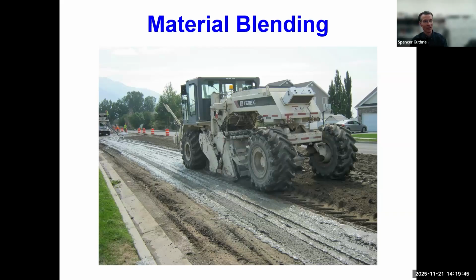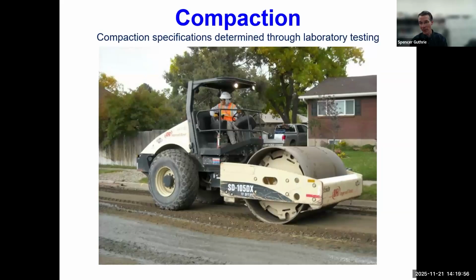So here's a picture. Again, no cement dust at all in a neighborhood, and we're strengthening significantly this layer with some cement. After that, we have compaction. Sometimes we see pad foot rollers, other times we see only smooth drum rollers, but the last roller to touch the road should be a smooth drum. It leaves a nice smooth surface. It can crown the road just right, and this provides the appropriate compaction.